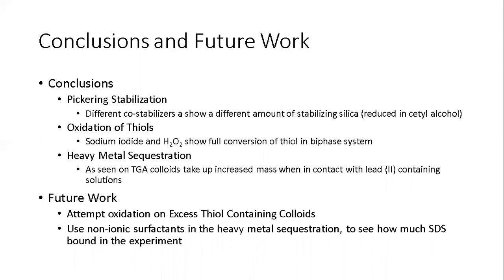Lastly, for heavy metal sequestration, you can see that the TGA took up extra mass, which is important because after we burn off all of the polymer, what should be left is the lead. So we definitely have some uptake of lead.